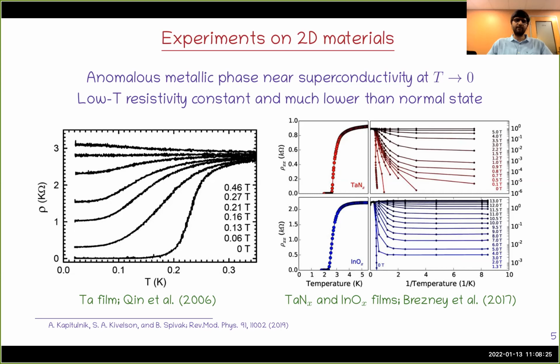For instance, this experiment is on Ta films. This is resistivity versus temperature, and different curves are for different values of magnetic field. At 0 field, you can see it's a superconducting transition, and at Tc the film becomes superconducting. Now you increase the magnetic field, and what you see is that the resistance decreases very sharply and it seems that it would become a superconductor, but it doesn't, and the resistivity simply saturates at some finite value. If you keep increasing the magnetic field, the value of this resistivity keeps increasing, but it's still much lower than, let's say, the normal phase value, which is somewhere here.